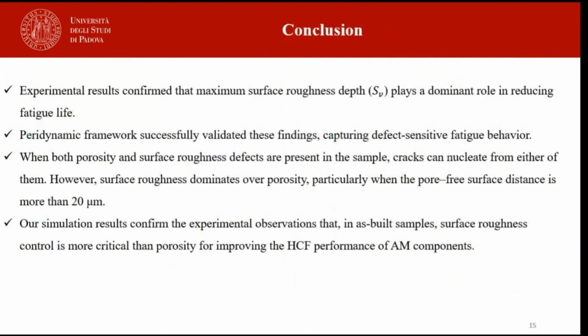Conclusion: experimental results confirm that maximum surface roughness depth in as-built materials plays a dominant role in reducing fatigue life. The peridynamic framework successfully validates this finding, capturing defect-sensitive fatigue behavior. When both porosity and surface roughness defects are present in the samples, cracks can nucleate from either of them. However, surface roughness dominates over porosity, particularly when the pore-free surface distance is more than 20 micrometers. Finally, our simulation results confirm the experimental observation that in as-built samples, surface roughness control is more critical than porosity for improving the high cycle fatigue performance of additive manufacturing parts.